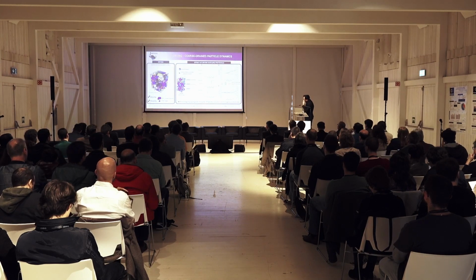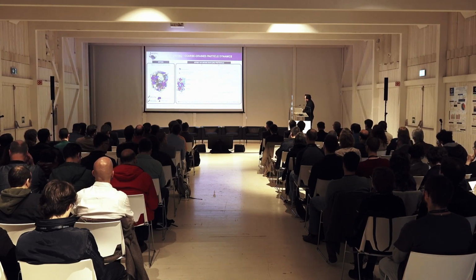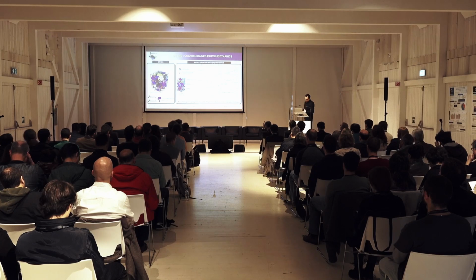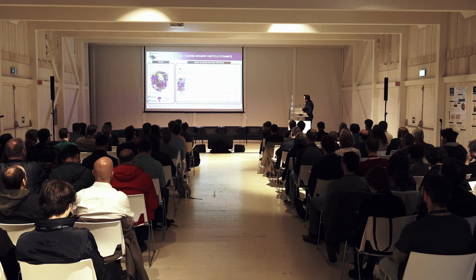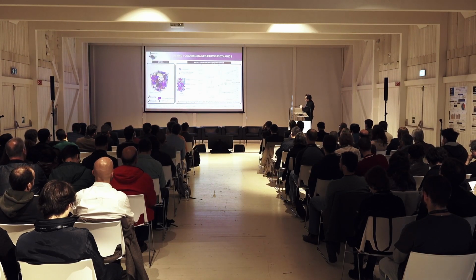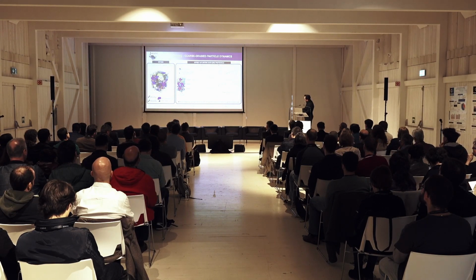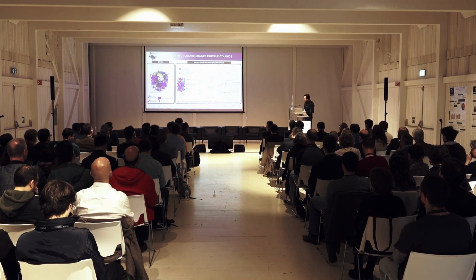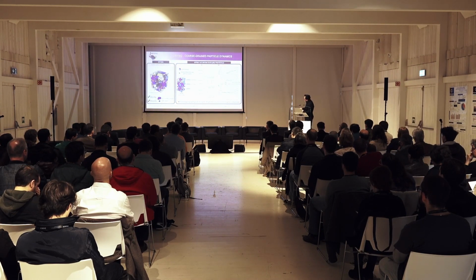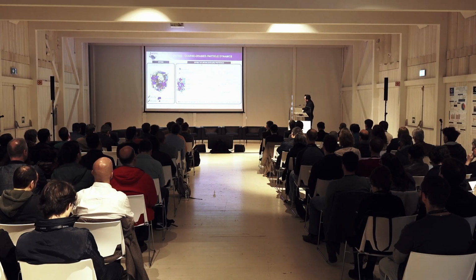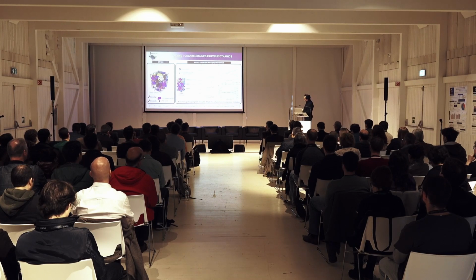And this model is also very useful because it can simulate different drying strategies. Okay? When you start, for instance, drying the slurry with a high drying rate, then you go to a low drying rate, or use more sophisticated protocols than this one. When you start with a high drying rate, you go to a low drying rate, and then a high drying rate again. And then you can analyze how these drying protocols will impact the way that the materials distribute in the thickness of the electrode. And you can, for instance, very nicely capture a phenomenon called CBD migration.